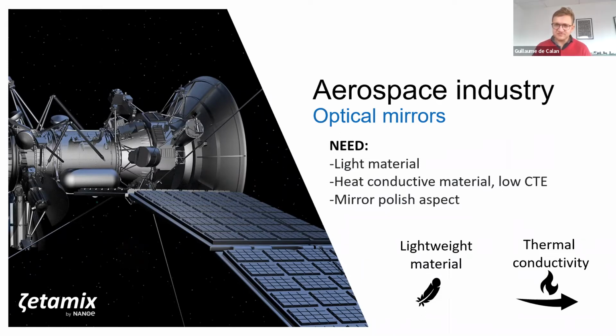Why is that? It's because we need a material that is extremely strong to withstand especially the launching phase, that's where it needs to be the strongest. It needs to be stiff so that it won't deform. You want a light material, of course, because sending weight in space is expensive. You also need a material that will not deform because of temperature differences. In space, you have huge temperature differences between the different zones, and so you need a material that won't deform whether it's hot or cold. And for that, you need a low CTE, and a material that's heat conductive, so that the temperature will be homogeneous on the whole material.